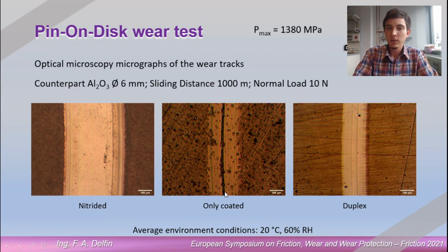believe is the DLC coating delaminated from the surface because of a problem with the adhesion, because we are applying here almost 1.4 gigapascal of pressure with these conditions we are testing. So we believe this sample couldn't withstand this force, this pressure, so it started to delaminate.